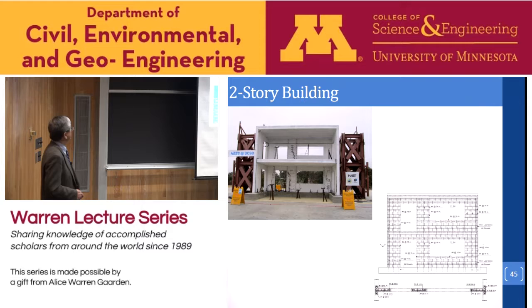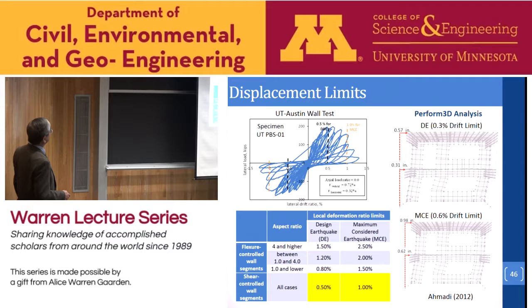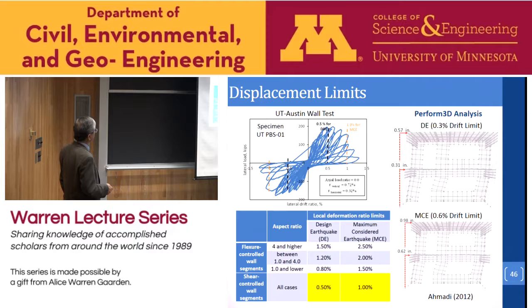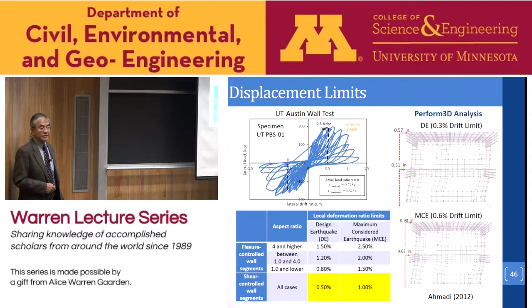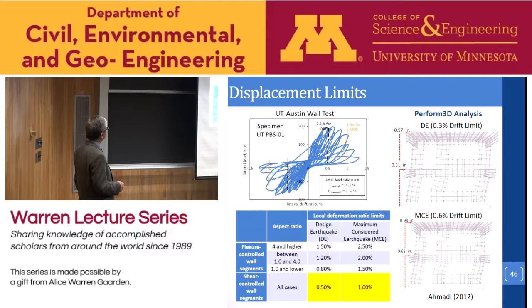The design was done at Texas Austin. Actually, the design criteria were based very much on the wall component tests with shear-dominated behavior in their lab. Because of these perforated wall systems, most of the failure will be shear dominated, like in these piers next to the window openings. So we have to limit the drift of these individual piers. Based on these tests, you can see that the drift at the peak is about 0.5%, and significant load degradation starts at about 1% drift.